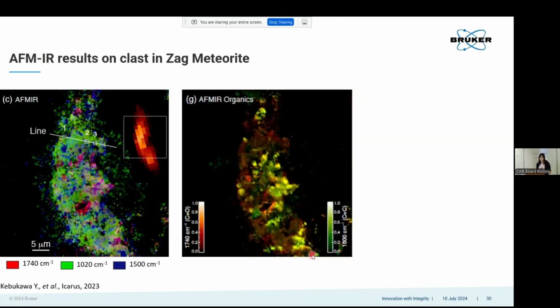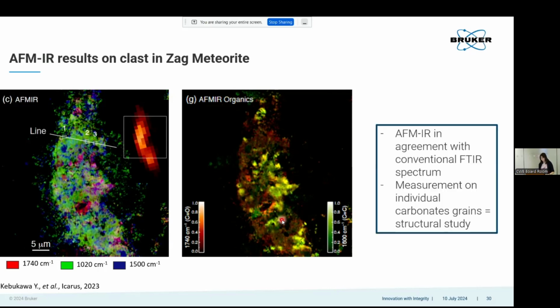And so in particular now we can look at just the organics, broken up from the substrate, where you see areas where the red is higher, you're seeing more of those carbonates. And when you're seeing the areas that are more green, you see the PAHs. And you see that almost always the PAHs are associated with a higher carbonate content, based on it being yellow over here. But in general, the carbonates don't need to be associated with the PAHs. So that gives you information on how they're sequestering.